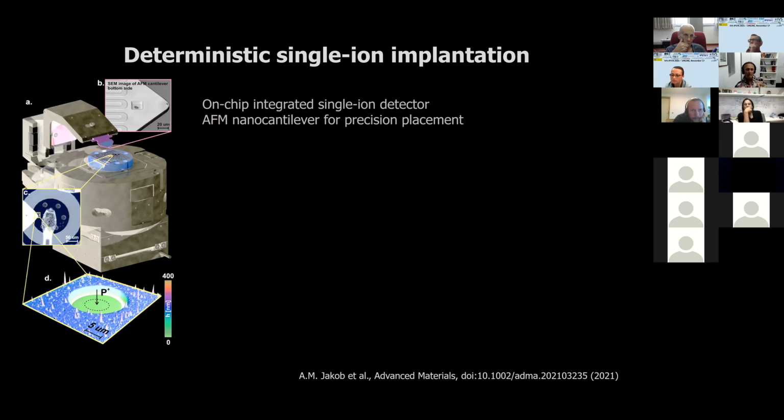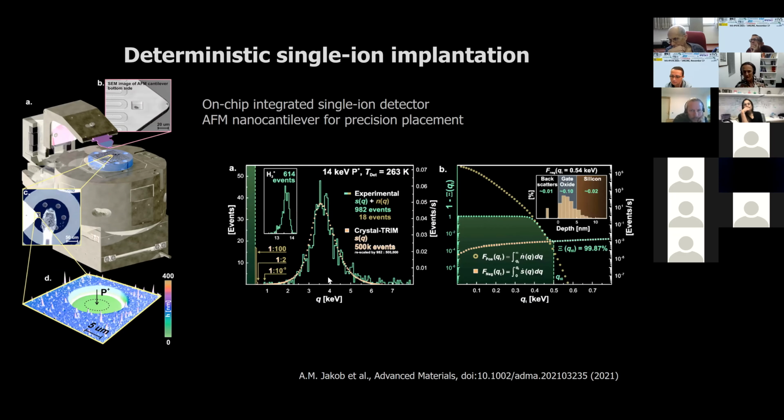Whereas we can implant single atoms and have a 99.87% confidence of having placed one and only one atom in the chip. This is a new technique. It's just being demonstrated now, and we are about to introduce it within the rest of the process flow.